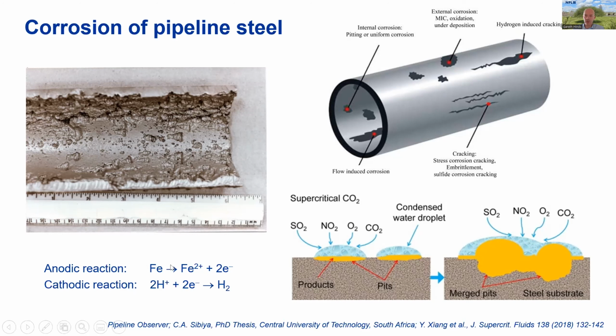And this can lead to perforation of the pipeline. If the corrosion is localized, this can happen quite quickly and be quite catastrophic, or you can just get general wall thinning of the pipeline over time, in which case people tend to build in what we call a corrosion allowance to make the pipeline wall thickness thick enough for the pipeline to tolerate this gradual wall thinning.